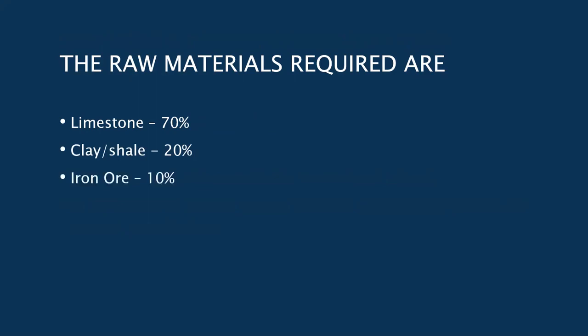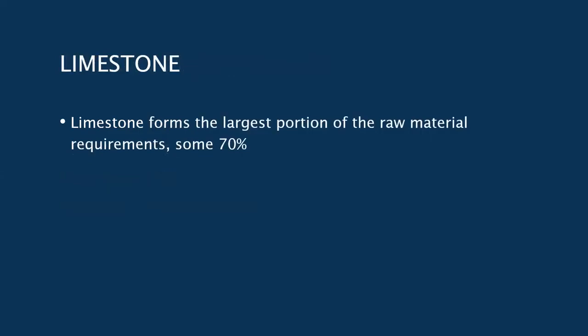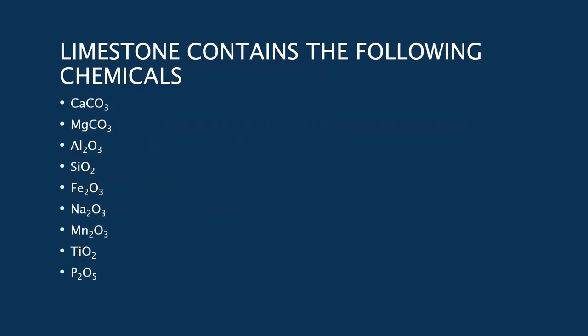The raw materials that we use in cement are limestone, as most people would guess. That's the high proportion, 70%. Clay, shale, that gives us the alumina component. Iron ore gives us some iron to add to it. Gypsum, and the gypsum is added after the process. I'll discuss that a bit later. Limestone, as you can see, is the largest portion, about 70%. Now, limestone is made up of a whole variety of minerals, including calcium, magnesium, alumina, silica, iron, etc.